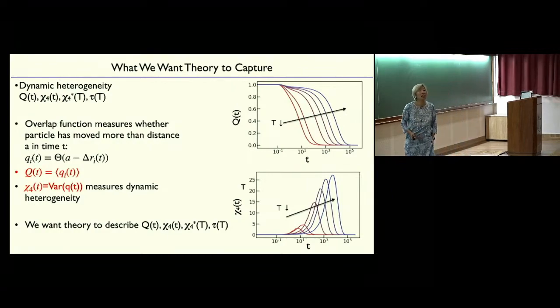Yes. So there are various ideas that close to the mode coupling, something qualitatively changes in the way particles move. So does softness tell you something? Does something change in the way softness behaves as you get close to the mode coupling crossover, or is it not sensible? We do not see anything like that as we go close to the mode coupling temperature. There's a very talented undergraduate, Shang, who's visiting my group and is working with Rahul Chacko and Sean Rideout on the polydispersed systems prepared by Monte Carlo swap, where we have really good data getting very close and going beyond the mode coupling temperature. And this description that I told you seems to be the same. It doesn't seem to change.